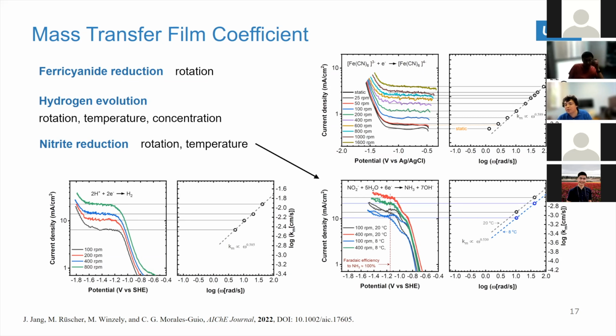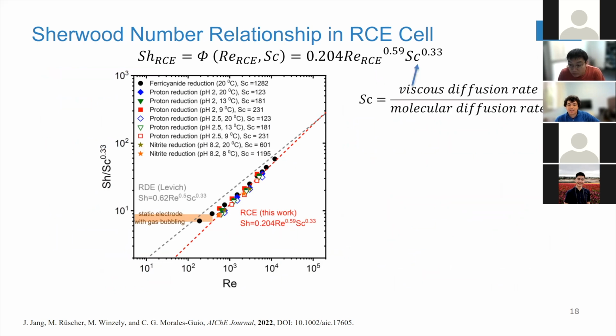We can quantify the total amount of ammonia, which is important because you might see a flow of electrons, but that doesn't mean that all your electrons are going into exactly the same reaction. So by coupling these analytical tools to the electrochemical cell, we can quantify the rate limiting step for the reduction of nitrite to ammonia. And as you change the temperature, that Km value also changes, as I mentioned before, because the diffusion coefficient changes as a function of temperature, density changes, viscosity changes for these systems. All those changes can be put into one dimensionless number, the Schmidt number, that allows you to account for viscous effects and molecular diffusion rates.